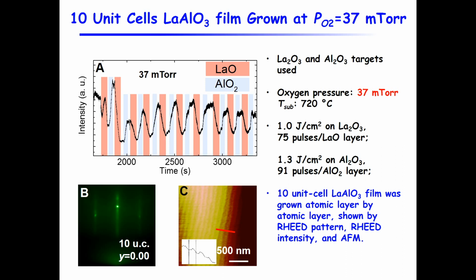Yes? So do the targets themselves bring oxygen? Because if I think about hybrid MBE that Susanne Stemmer does, she has precursors which bring oxygen to the substrate. Is that happening here, or are you able to just grow at higher pressures and that's why you have better oxygenation? I don't think there is a simple answer to your question, because during pulsed laser deposition, there are all kinds of things in the plume.